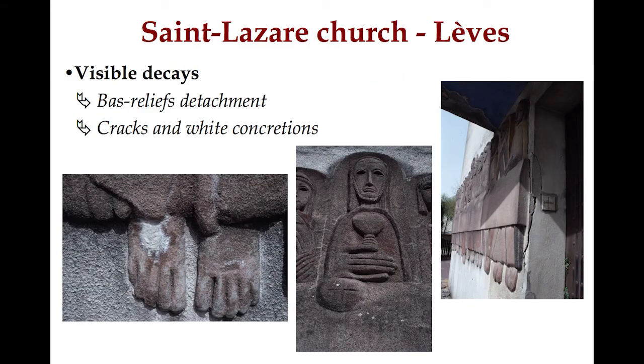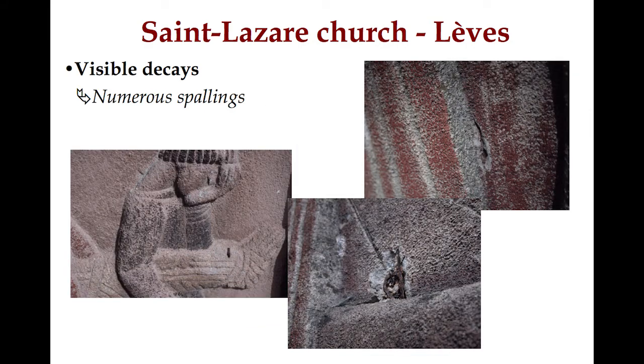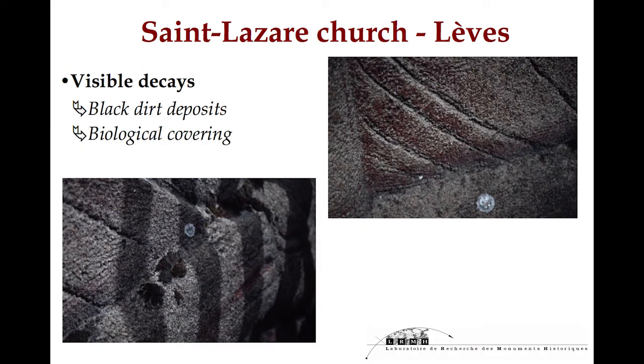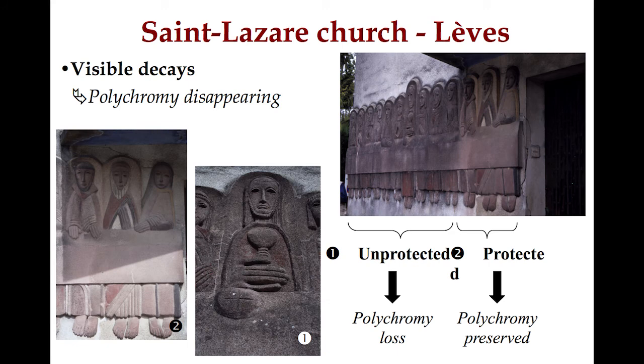So, concerning the visible decays of this bas-relief, we observed bas-relief detachments, cracks and white concretions. We observed numerous spalling, here, and here, and here. And we observe black dirt deposits and biological covering. We observe the polychromy disappearing. Where the bas-relief was not protected, there was a polychromy loss, and where it was protected, the polychromy was preserved.